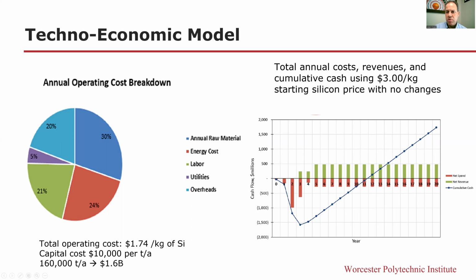And so with a $3 per kilogram price of solar silicon, we're looking at about a 10 to 11 year break-even time on the plant. So a significant cost reduction in addition to eliminating the CO2 emissions and the other benefits of this, not even counting any sale of the high purity oxygen byproduct.